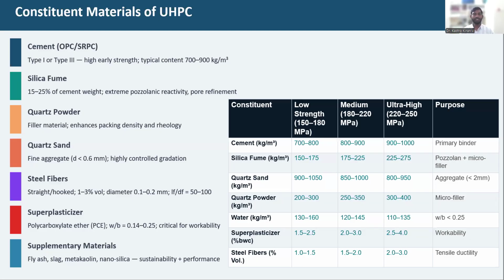And the silica fume percentage will typically be between 15 to 25% by weight of the cement. Again, we can reduce this silica fume content also. So in the present work which I'm currently doing, we are not even using silica fume, but still we are able to attain 130 to 140 megapascals of strength. However, we are using microfine silica as an alternative for silica fume, but that is also at a very minimal level.